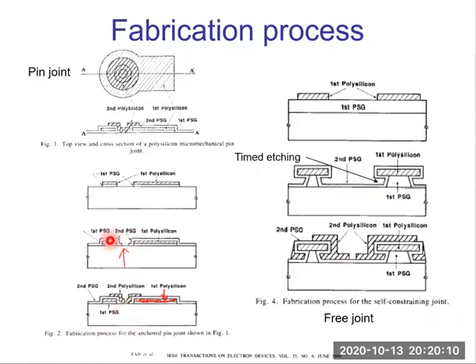But for pin joint, we can see the cap, poly 2, the second polysilicon layer, is anchored to a substrate, so it only allows rotational movement. Questions? So in this slide, we can clearly see the relationship and the difference between pin joint and free joint. They can be fabricated simultaneously on the same wafer with the same surface micromachining processes, except that for free joint, the second PSG layer is not patterned for anchor hole. So there's no anchor hole for free joint. But pin joint has an anchor hole. So that's the difference.